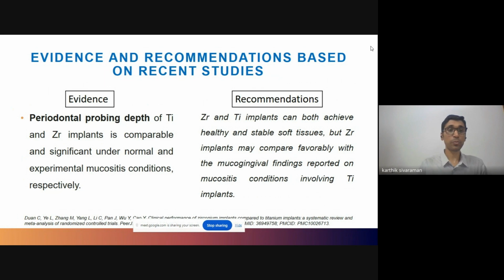The next evidence is pertaining to periodontal probing depth, and here they found comparable results under normal mucosal conditions, and a significant difference under mucositis conditions. So if it's a normal mucosa, the periodontal probing depths were quite similar, not statistically significant. However, if it's a mucosa exhibiting mucositis, the periodontal probing depth showed variation. So what is the recommendation of the author? They said that zirconium and titanium implants can both achieve healthy and stable soft tissues, but zirconium implants may compare favorably with the mucogingival findings reported on patients exhibiting mucositis conditions.